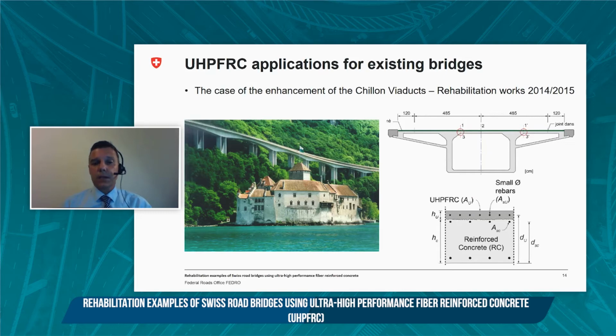It was thus necessary to develop a concept for rehabilitation and strengthening to protect the concrete from water ingress, slow down the rate of alkali aggregate reaction, and increase the ultimate resistance and stiffness of the deck slab and girder in view of potentially reduced strength and modulus of elasticity of the existing concrete. Such an intervention had to be cost-effective in terms of direct construction costs and also of user costs. It also had to preserve the form and hence respect the cultural value of the bridges.